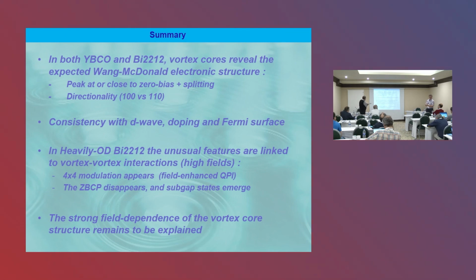understand from our measurements is that concerning the heavily overdoped side, the modulation and the presence of the zero bias anomaly are all linked to the vicinity of the surrounding vortices. We don't understand why the zero bias anomaly disappears and gets into finite energy states. We tried to model by decreasing the distance between vortices, and we were never able to get the finite energy subgap states from the zero bias anomaly. So we still don't understand the strong field dependence of the vortex structure. Okay, with that, thank you for the attention.